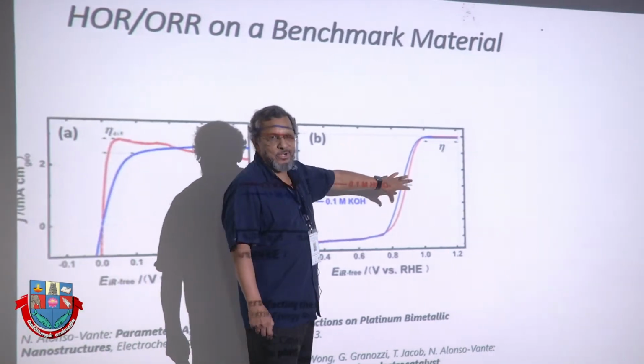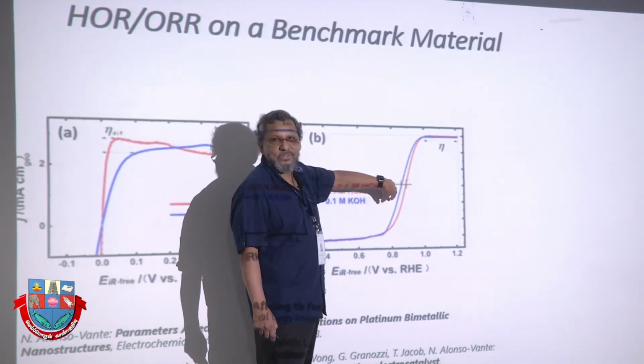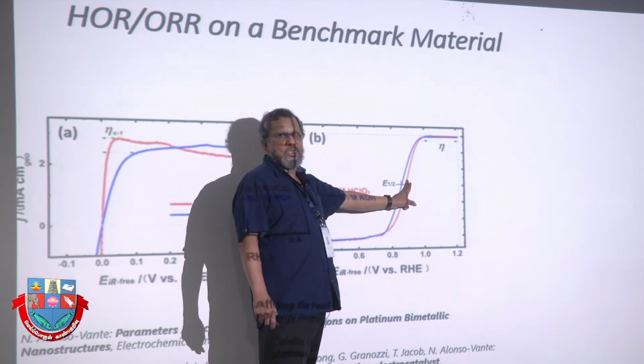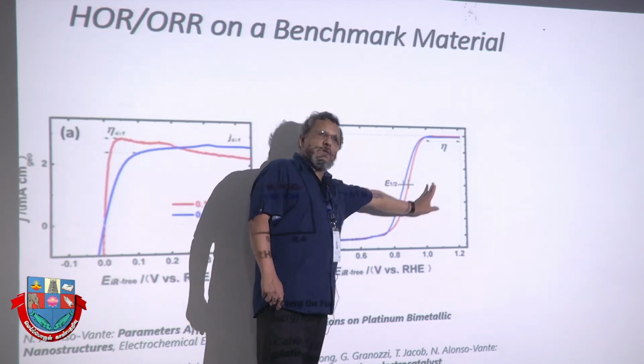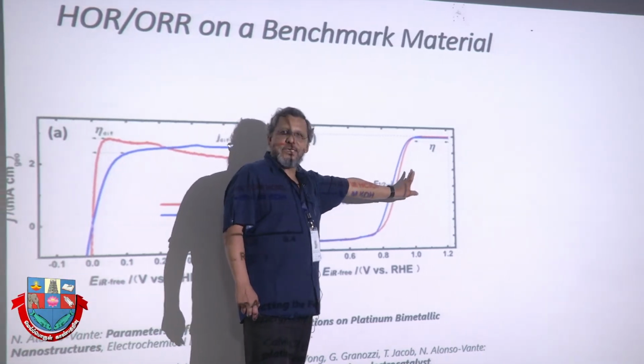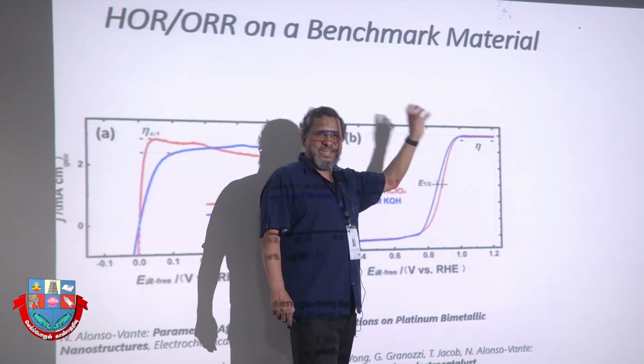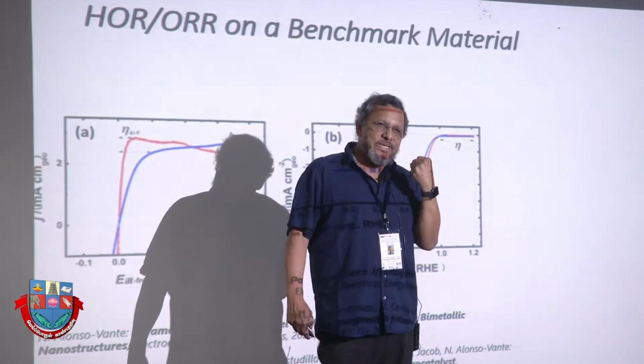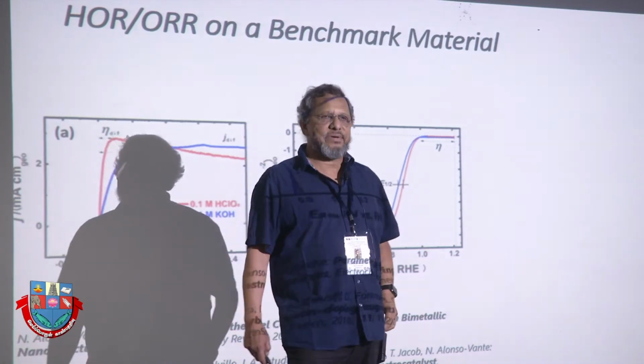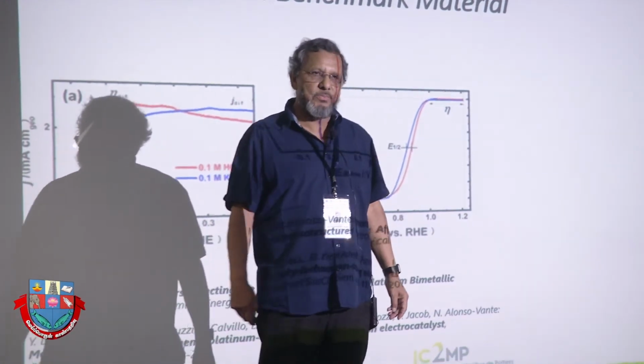A similar effect we observe when we do the oxygen reduction reaction. So the half-wave potential here is shifted to the left instead of going in that direction. That also means that the complex chemistry at the surface is rather different. And that's one thing that we have to think of.